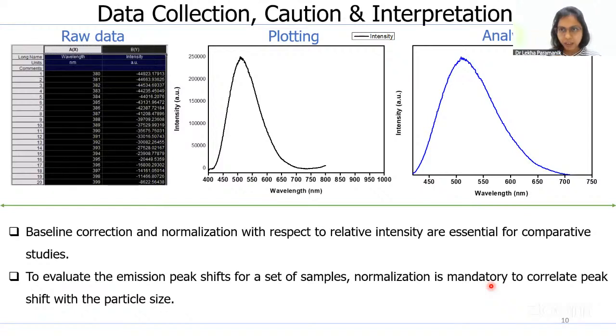I would like to share about PL data interpretation. Contrary to the FTIR and UV, in PL, at first we have to give an excitation wavelength as input. Thereafter, we can collect the PL signal of the corresponding sample. Then this PL data is plotted as shown here, and we can adjust the wavelength region for better appearance in our manuscript. The baseline correction and normalization with respect to the relative intensities are essential for our studies to evaluate the emission peak shift for a set of samples. Normalization is also mandatory to correlate the peak shift with particle size.